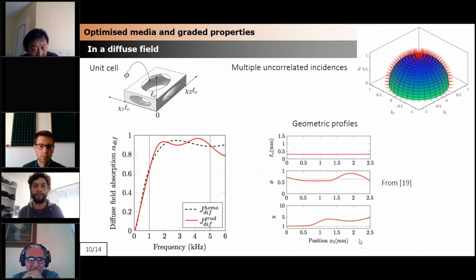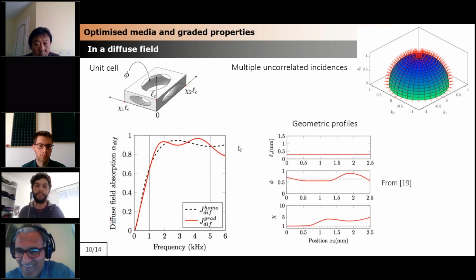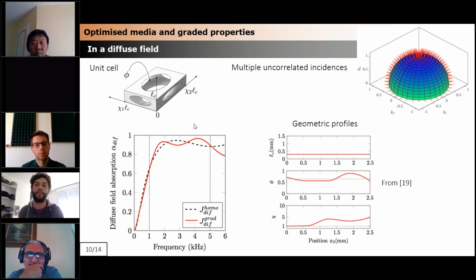What we see now on the bottom left corner is the dashed black line, which is the optimized homogeneous material between 1 and 5 kilohertz for all of these incidences. We see we only have one peak of absorption in this 1 to 5 kilohertz range. This is for a 2.5 millimeter sample. When we grade the properties and allow them to be anisotropic, we can bring back another maximum of absorption in this frequency range, which allows us to maximize the absorption on the whole range, because the second zero has been brought back into this optimized frequency range.